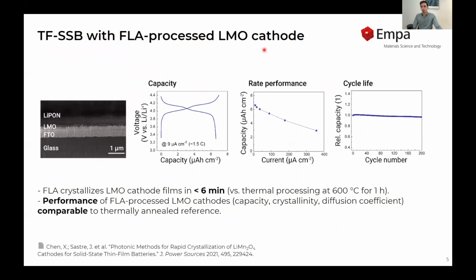By using the FLA process for LMO, we were able to fabricate a thin film battery on a temperature-sensitive substrate, FTO-coated glass, with the LMO film crystallized by FLA, and then LiPON and lithium metal on top. We observe we are able to obtain almost the theoretical capacity of the cathode film. Rate performance is as expected. And we also observe a very good cycle life, so only 3% degradation after 200 cycles.